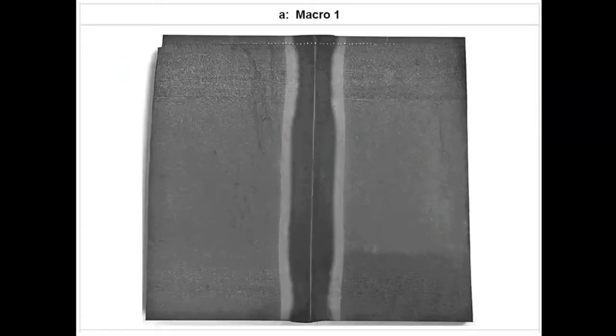Just quickly look at the anatomy of a flash butt weld. So here you can see a macro. This is a slice through the middle of the weld. That line down the middle is the fusion line. It's decarburized slightly, so you have some continuous grain boundary ferrite networks, which is giving it that lighter color. Either side of the fusion line, you have the critical heat affected zone, and then you have this light gray zone, and then we return to the bulk.